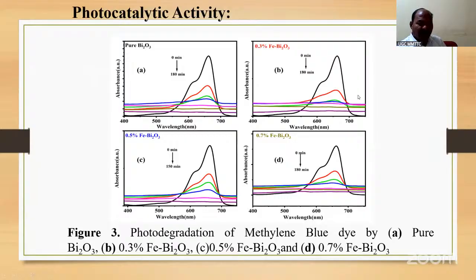Then the photocatalytic activity of this. Here is the photodegradation of methylene blue dye by pure and iron doped samples. For the pure sample, at 0 minutes, how much time does it take? That is 180, and this peak. Now you see this is for pure. Here the time is reduced, the height of this peak decreased, and for this again it is decreased. Dye photodegradation.